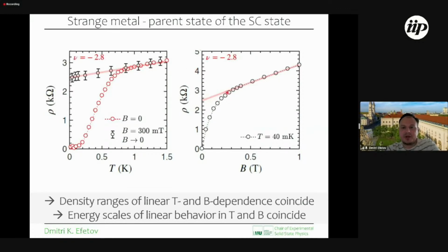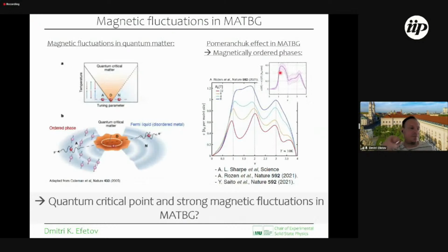Same happens for the magnetoresistance. And of course, basically, this allows us to ask the question about the parent state of the superconductor. So in principle, by all means, the superconducting phase is born out of a strange metal phase. Whether the mechanisms for the one or the other are related is a completely separate question. But at least the superconductor and the strange metal phase are coinciding here. And so with this, I think this field is opened up for interpretation now.